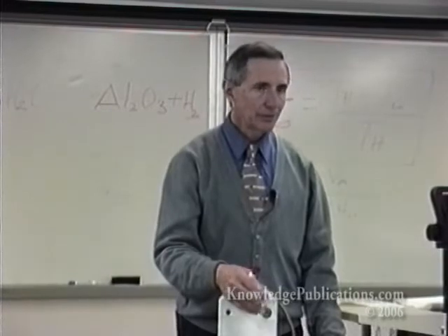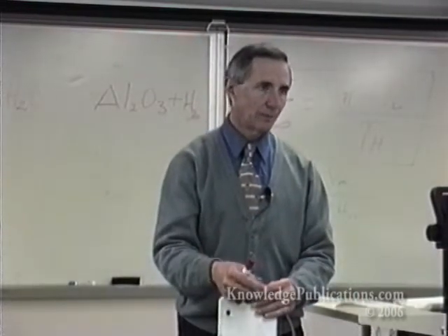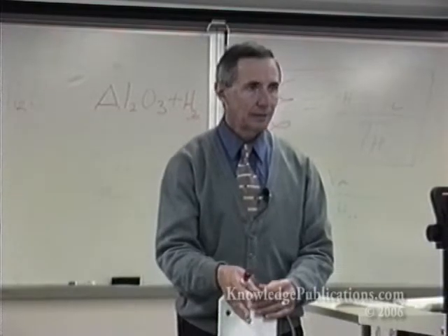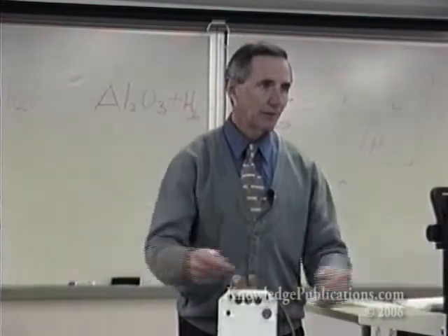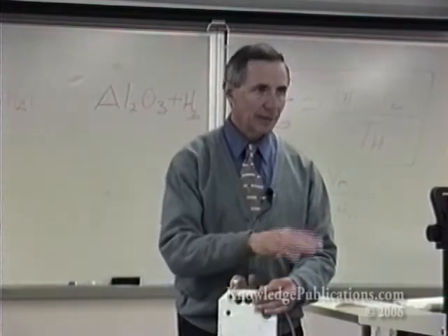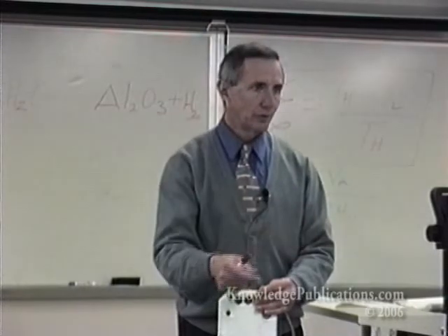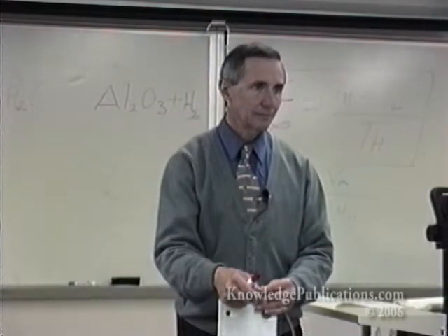The baking temperatures are moderate. They can be 250 degrees if you hold them for a while. At 300 degrees, it's less time required. At 350, it's even less. And these are exponential, as it turns out, in terms of hydrogen diffusion out of metal lattice.